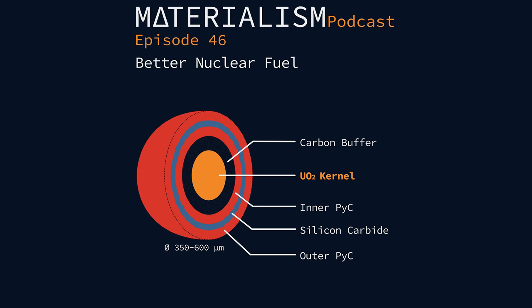Now, is that at the atomic level mixing, or are these like bulk particles, like a composite mixture? This is more of a composite. And the advantage here was that you could have the manufacturing benefits of uranium oxide, but the higher temperature benefits of uranium carbide. Gotcha. And so theoretically, there were quite a lot of benefits to this, but Germany decided to stick with uranium oxide, and they decided to adopt that as their standard.